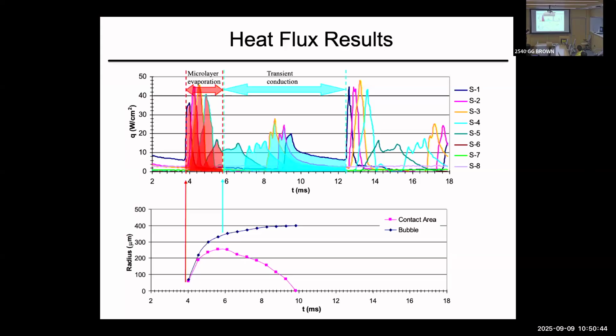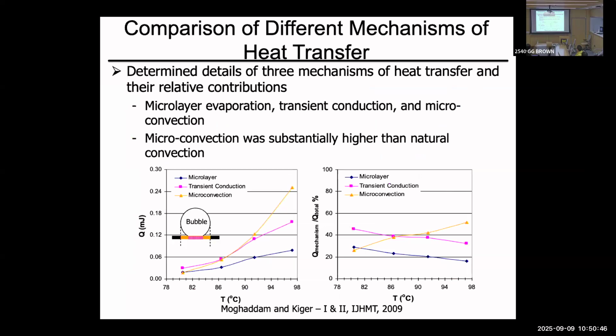So this allowed me, for the first time, to take over an area the size of a bubble to differentiate how much of the heat is transferring due to microlayer evaporation, how much is happening due to convective transient conduction, and how much heat is happening due to micro-convection. So what we realized is that at higher temperature, essentially a substantial fraction of the heat is